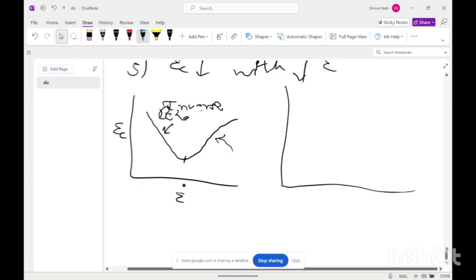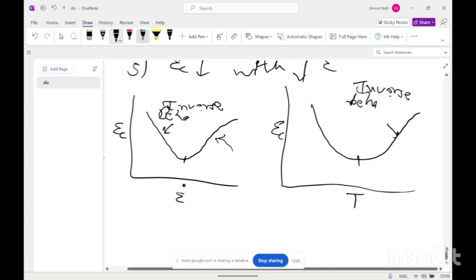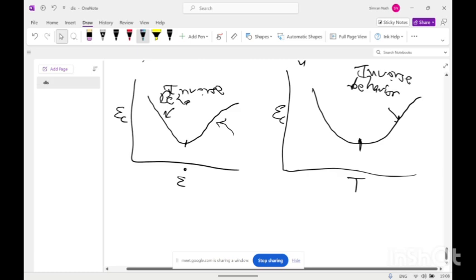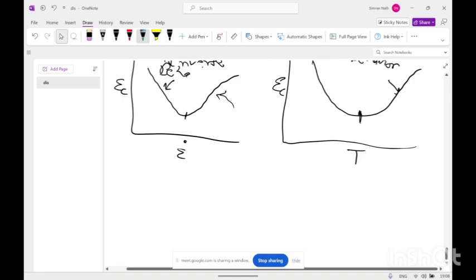And similarly, if we draw a graph between critical strain and temperature, there will also be an inverse behavior. So with increasing temperature, the critical strain decreases. After some point, if temperature is very high, the critical strain also increases. Because at higher temperature, there can be complex interaction between the solute atoms, dislocations and obstacles coming in the path of dislocation.